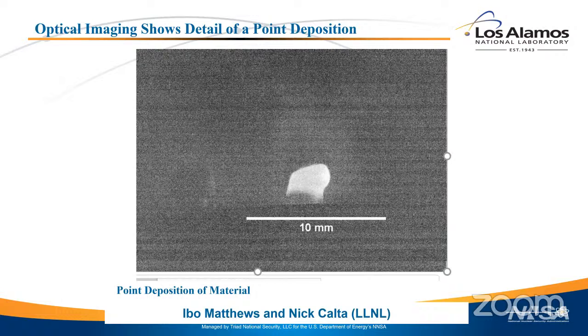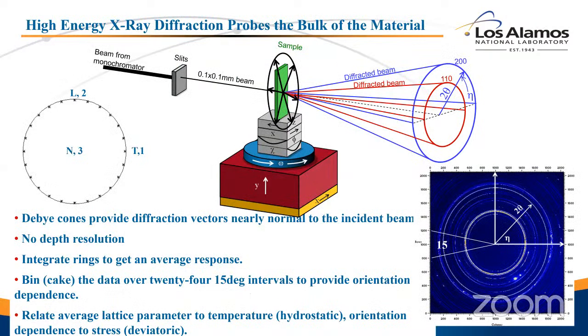And while this is happening, we're passing X-rays through that bubble, which is the glowing part. It doesn't look like a bubble now because it's wiggling, because it's liquid. We'll see the liquid and we'll watch that as it solidifies, and we'll watch the texture and the phase transformation. This is 304L stainless steel. It solidifies in the ferrite and it transforms to the austenite. And we're going to attempt to watch all of that happen with the X-ray beam and pull out microstructural features as it does happen.